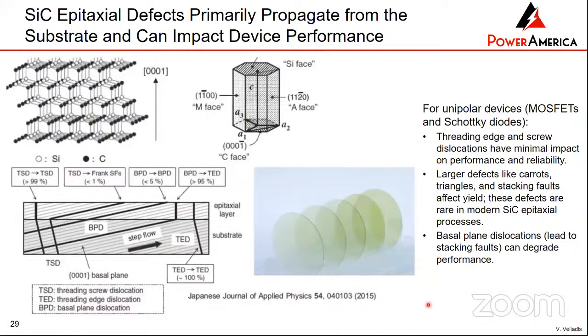Okay, so there are several defects in silicon carbide. And again, I will point out that silicon is a very, very clean material, and that's a huge advantage. It's been around for 60, 70 years, and it's been perfected in its growth. But for silicon carbide, there's threading edge and screw dislocations that tend to be benign. They do not cause a problem. There are larger defects like carrots, triangles that have been mostly eliminated. The one defect in silicon carbide today that's actually being a problem with making high voltage devices are basal plane dislocations. And basal plane dislocations can degrade performance. So that's the one defect that's shown here, BPD, basal plane dislocations, that the silicon carbide community is trying to eliminate.